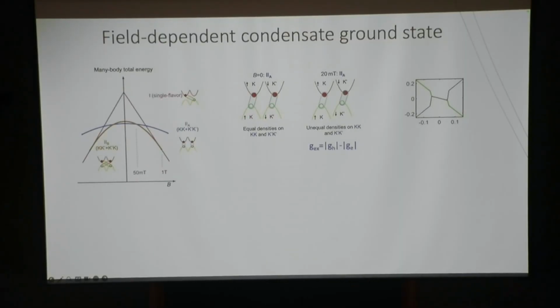When you apply a finite magnetic field, the energy of these two becomes slightly different. So the density of these also becomes slightly different. But because the G factor is equal to the hole contribution minus the electron contribution, the net G factor is small. So as a result, the susceptibility will be weak. So you have a very small slope. But also what you can see is it will listen to what the hole wants to do. So it will go with a spin polarization along the hole direction. But it's actually opposite to what the electron wants to do. So as a result, the electron spin energy will increase, but the total exciton energy will decrease. So what you can see is something like this, a small slope along the hole polarization direction, but the electron polarization direction is actually opposite to what it naturally wants to do.